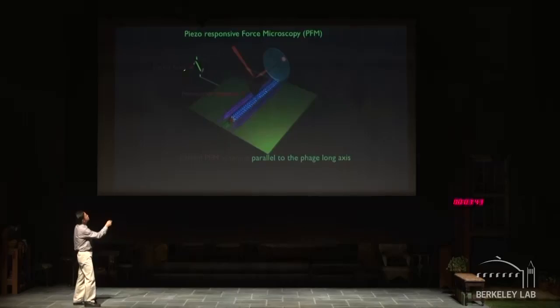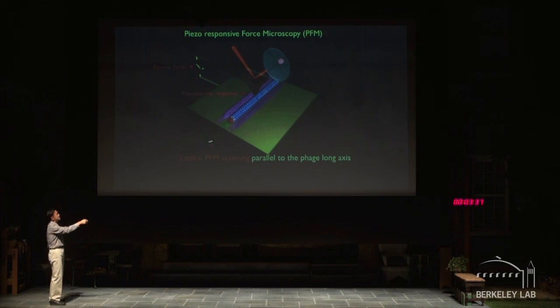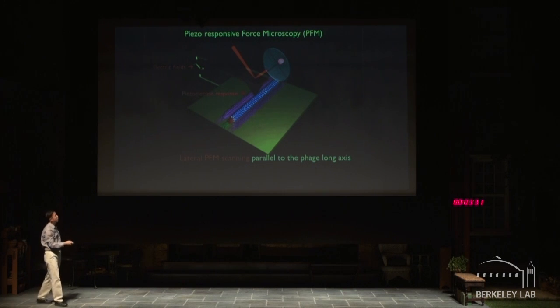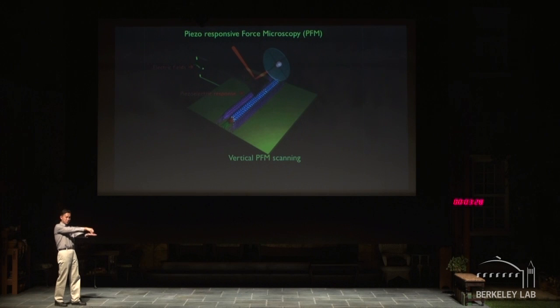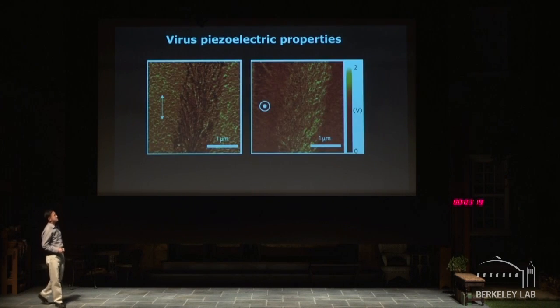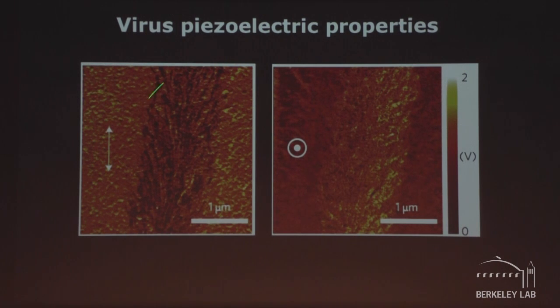To prove this concept, we used a special microscope called the piezo responsive force microscope, which has a long tip that touches nanoscale substances in a very specific manner. During that time we apply an electric field, which induces mechanical force in the viruses. Depending on the mode, we can measure their pushing upward, downward, or out-of-plane forces generated from these materials. Using this microscopy technique, we first proved that our viruses have a piezoelectric phenomenon.